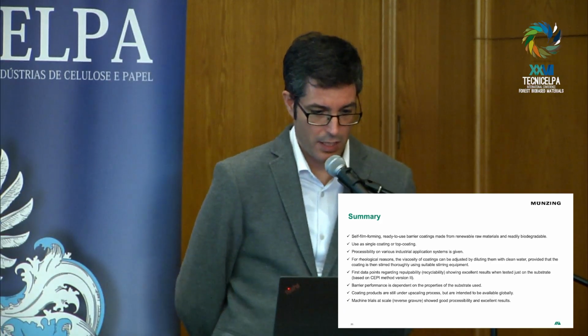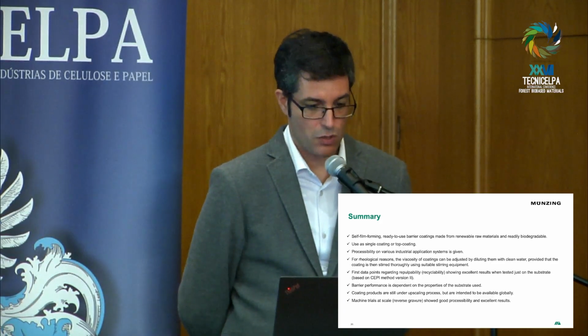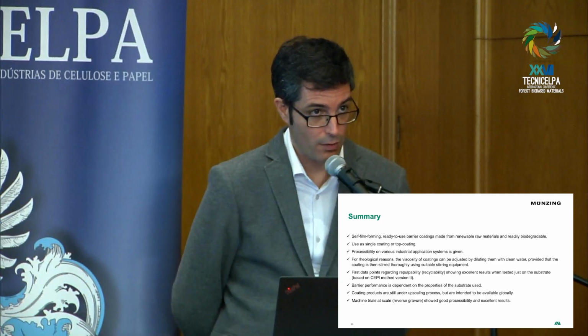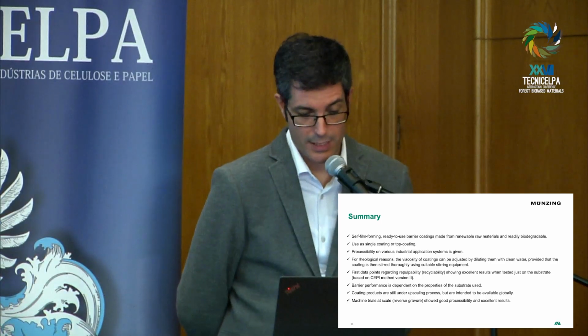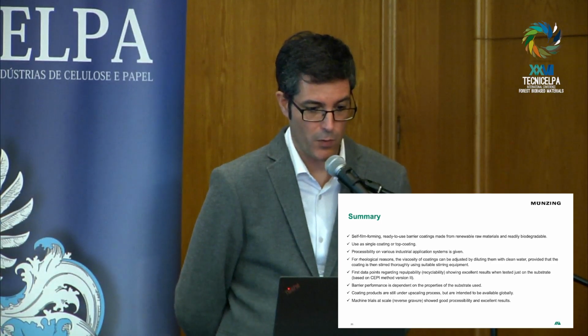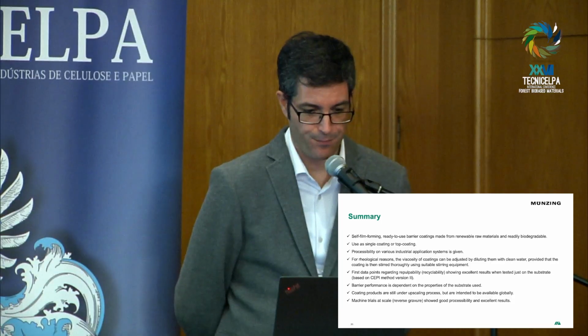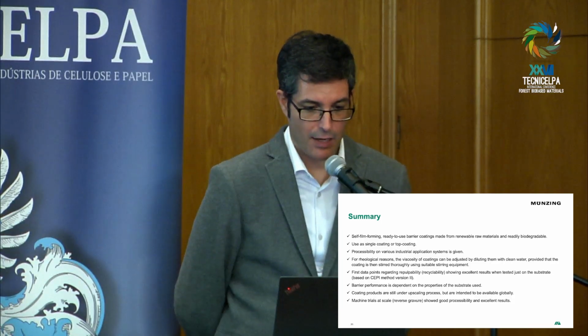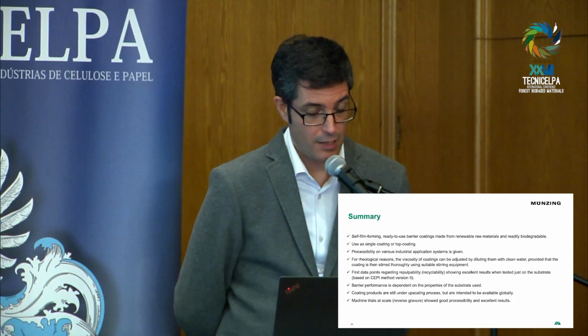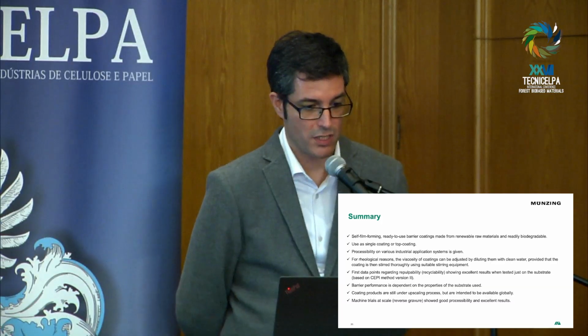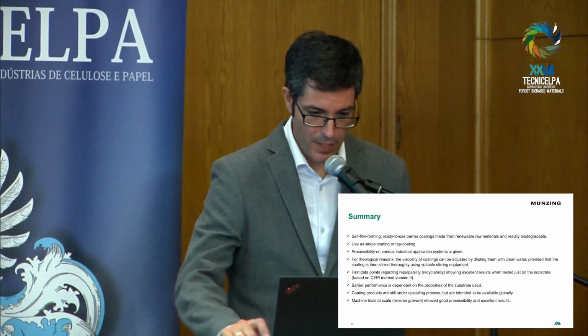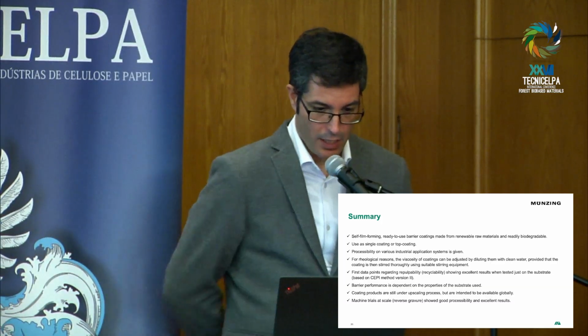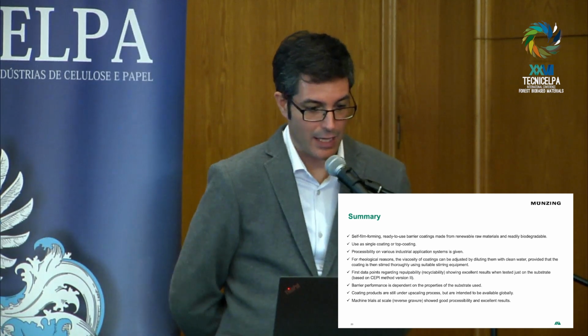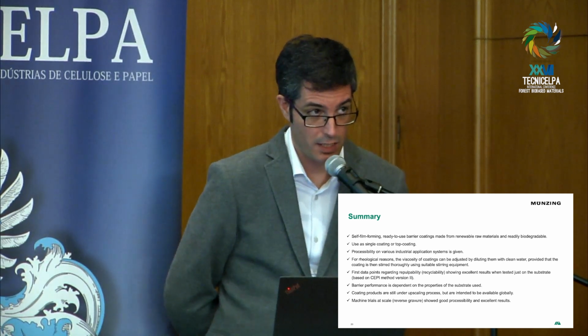These coatings will be scaled soon. In fact, the 3220 is already available. It's a standard material. We developed a few batches in production, and with the V15/8, we expect to have it soon because it's still on aging tests. And finally, the machine at industrial scale also proves very good processability and excellent results.